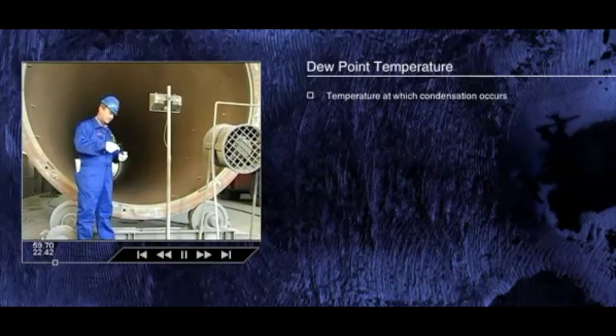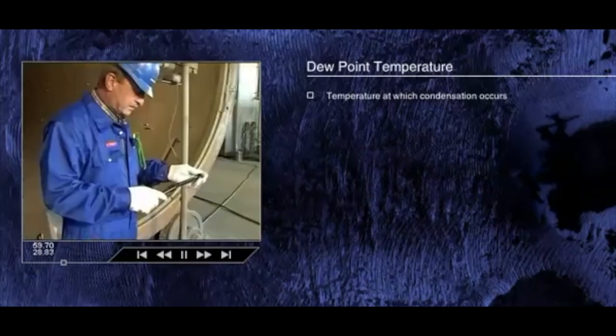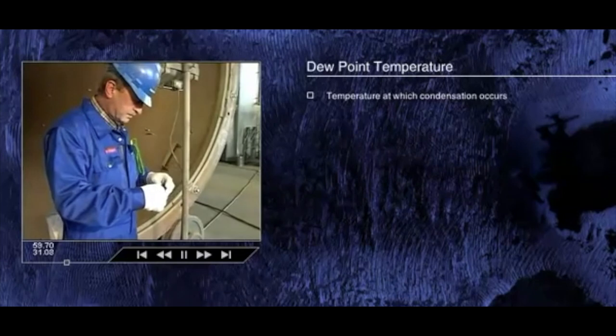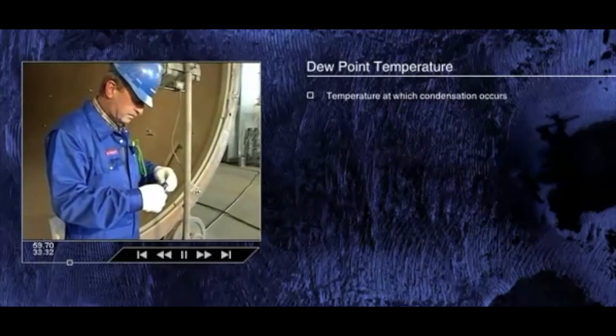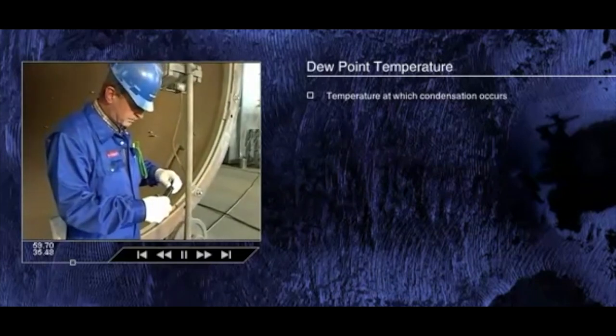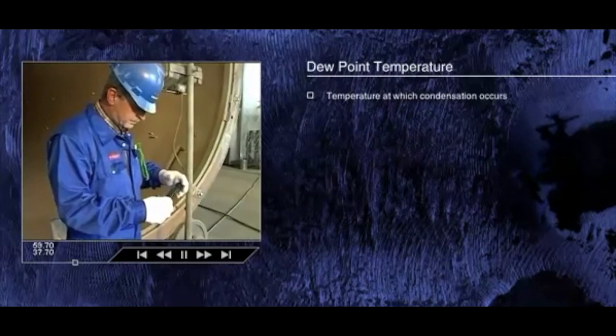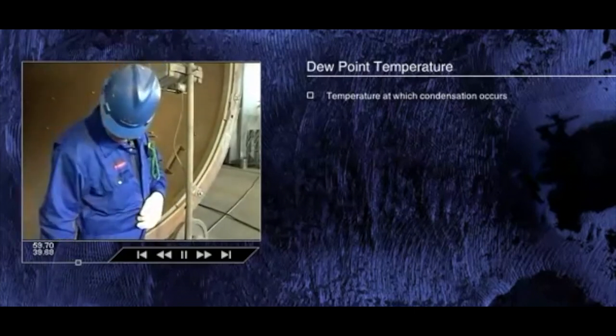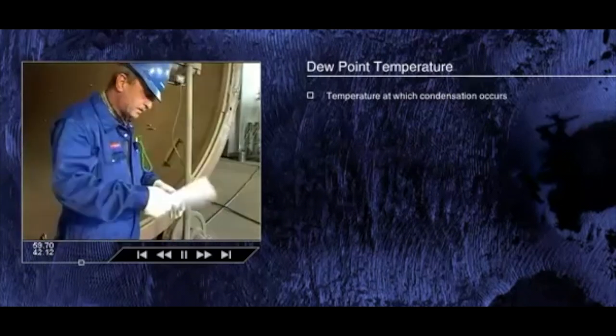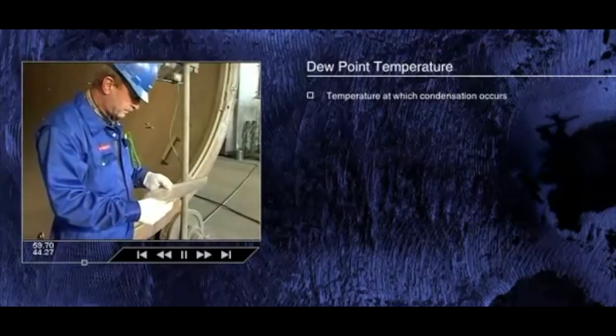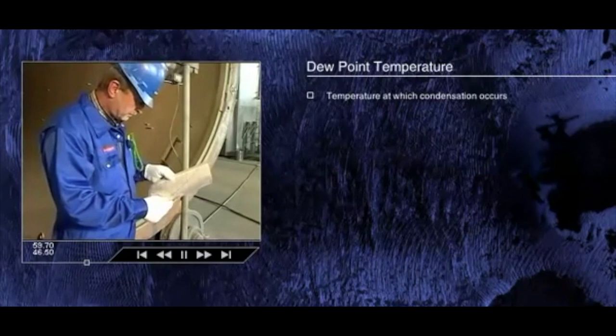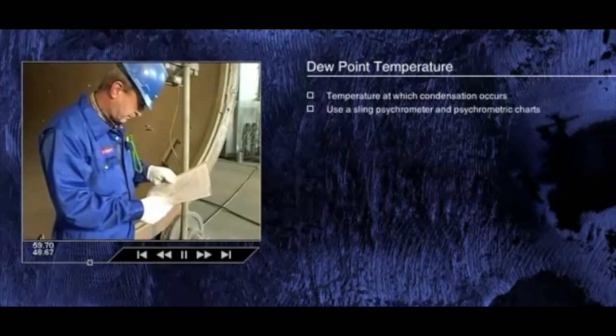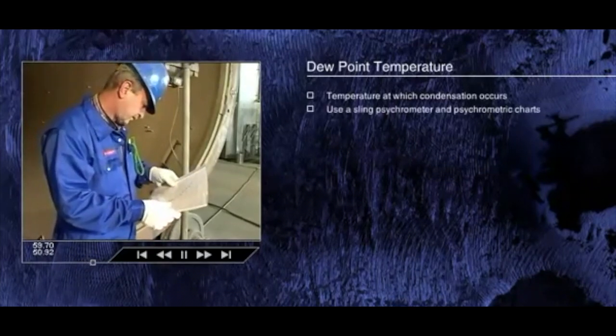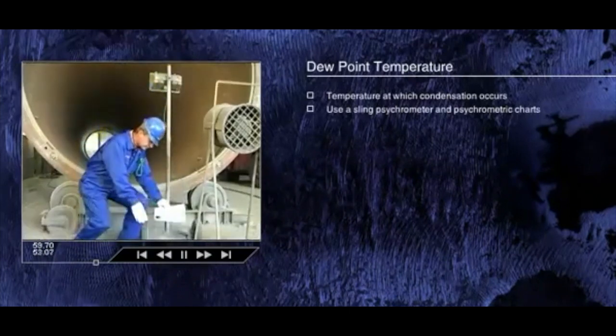Coatings applied over a wet surface will generally not achieve adequate adhesion to the substrate. If abrasive blasting is performed when environmental conditions are close to the dew point temperature, condensation is likely, and flash rusting may occur. The relative humidity and the dew point can be determined using a sling psychrometer and psychrometric charts, which are discussed in the inspection module of this program.